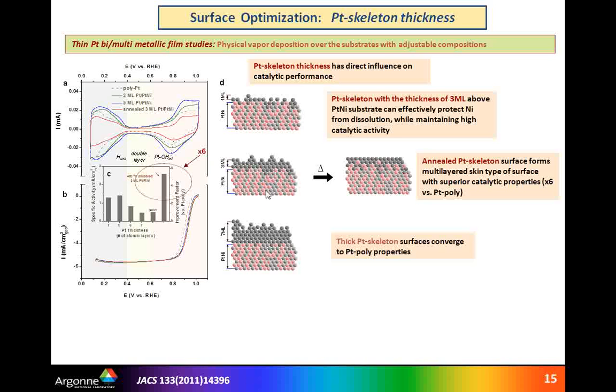So from that point, the main challenge was whether annealing of platinum skeleton, which is as thick as 3 monolayers, would bring and resemble properties of ideal platinum skin 111. So we gently annealed that again at a temperature somewhere around 400 to 500 C, and we could see that properties were substantially changed, and specific activity was increased by a factor of 6 compared to polycrystalline platinum. And that was a clear indication that we were able to achieve platinum skin type of behavior.